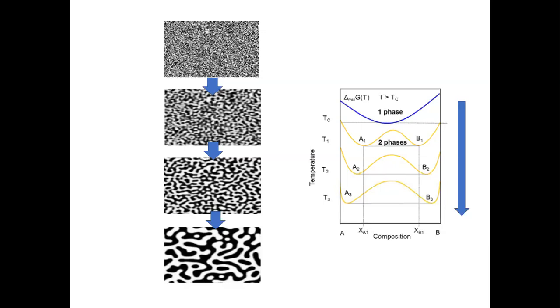And if you cool the system, we know just from the thermodynamic consideration that the free energy is going to develop a local maximum. This means that if you start with a composition right in the middle, for example, this composition will not be thermally stable, because by separating into two different phases with distinct compositions, as suggested by the free energy curve, we can lower the free energy of the system. So this is what the system will do, to lower the free energy by separating into two different phases. And this is basically the phenomenon of spinodal decomposition.